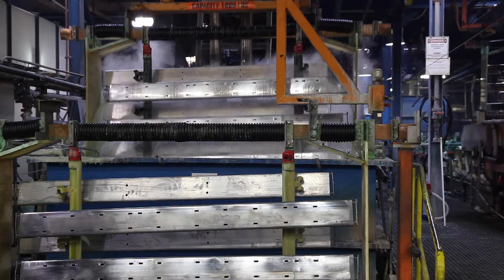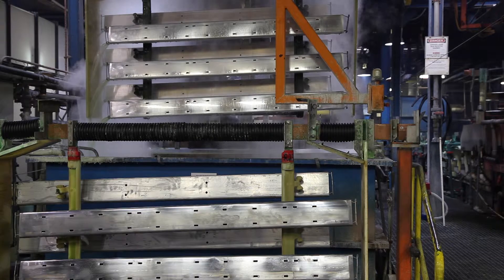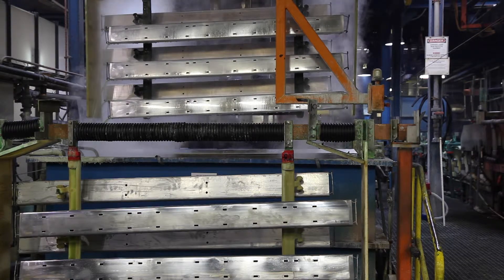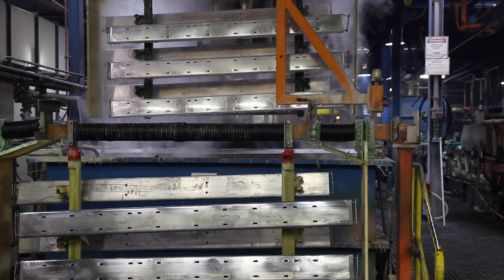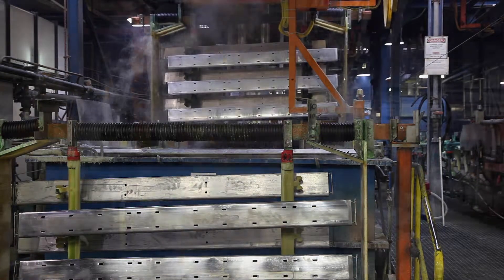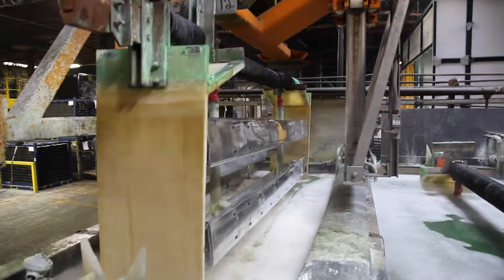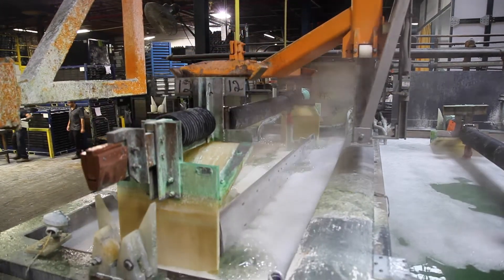What really makes the part look brilliant is the bright nickel process. The bright nickel has additives to improve the appearance and is the second thickest layer of the four. The final nickel layer is the microporous nickel — a thin layer that has thousands of small particles in the deposit which prevent large sites of corrosion.